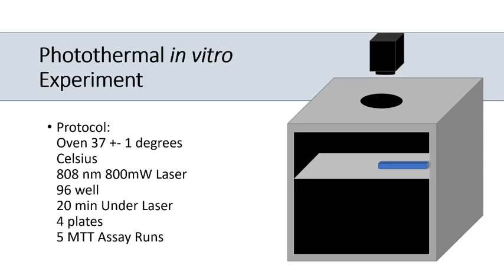So what we did was we set the laser up at the top, and we would look through the top of the oven and slide the plate over and get it lined up perfectly. And we had to practice doing this a lot. Ended up standing on a counter trying to get in there and make sure it was exactly right. And the cells can't be out of the incubator for more than 2 hours, so that's why it's so important that we do this quickly.